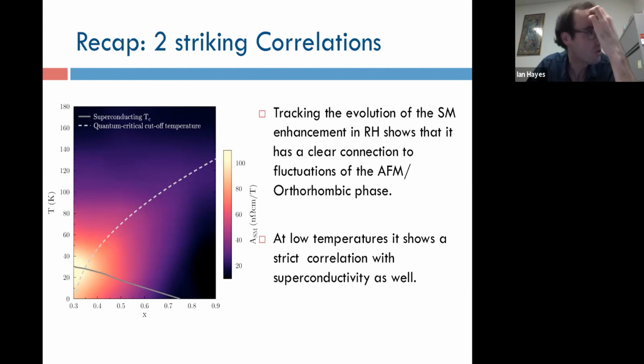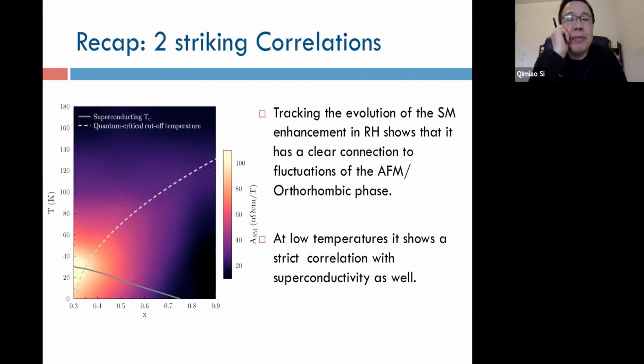temperatures. Can you describe what accounts for that difference between vanadium doped chromium and the heavy fermion material? Yeah, it's tied up with the very drastic Fermi surface change on the two sides of the quantum critical point that happens in a heavy fermion system that doesn't happen in the more conventional spin density wave quantum critical point.